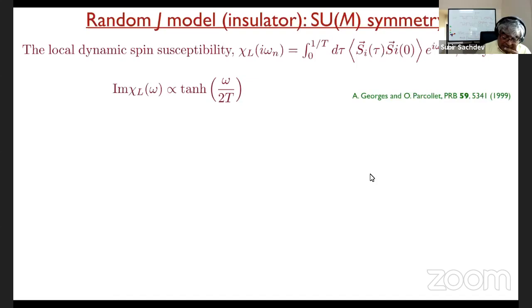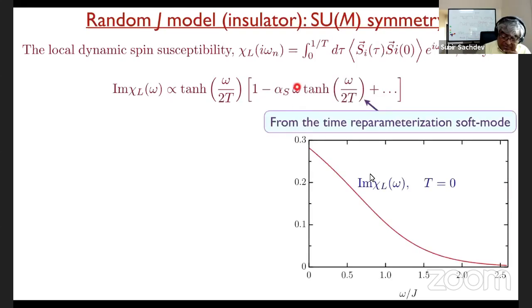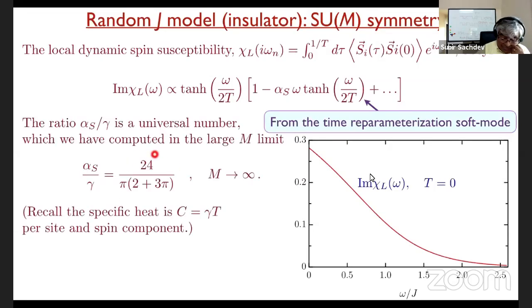But what we can do is actually now even compute the correction, and this is the numerical computation, and it fits this form extremely well. We can only do the numerics in this case at 0 temperature, so it's linear in omega as shown here, and this coefficient alpha sub s is related to gamma, and you can compute in the large M limit anyway what this number is. So we have these corrections to the susceptibility. So this thing, of course, is at T equals 0. So if you go to negative omega, it's going to have a discontinuity. Whoops. And that should be below 0.